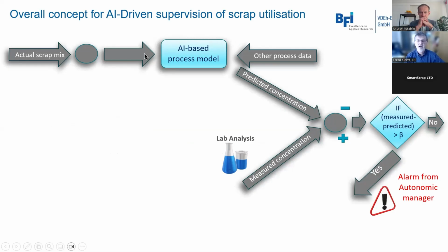We have the AI-based process model, which uses the scrap mix which has been charged for every heat, and other process data like oxygen input, lime input, and so on, to predict the element concentration. Then this predicted value is compared to the measured concentration, which has been determined by a laboratory analysis. And if the difference between predicted and measured concentration is higher than a threshold, an alarm is created from the autonomic manager, which says something is wrong.